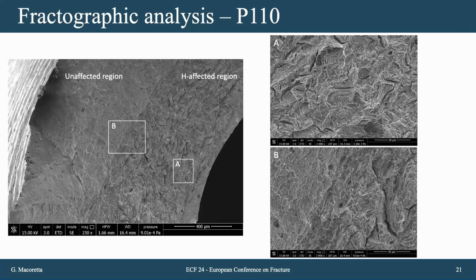And if we look at the whole cross-section, the black portion of the image is the internal wall of the specimen. We have a hydrogen-affected region that covers at least half of the thickness of the specimen. The thickness is 2 millimeters, and the external diameter of the specimen is 7 millimeters. Here you can see a hydrogen-affected region where transgranular fracture traces are evident, a transition region, and a region that is almost unaffected by hydrogen.